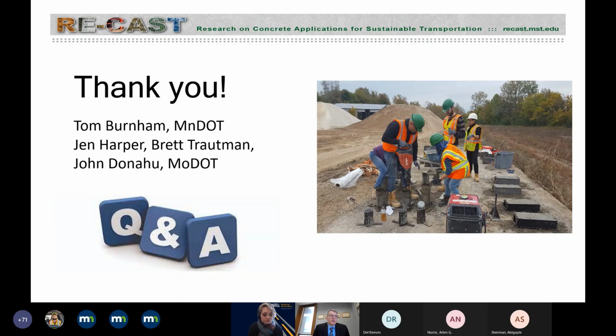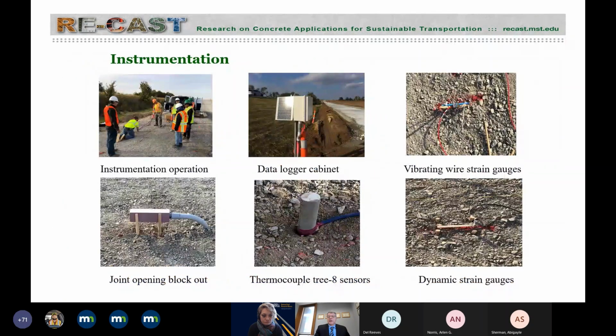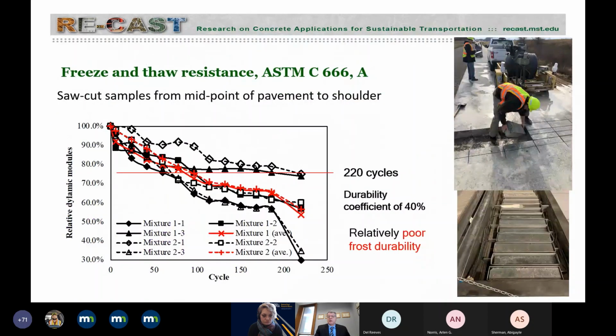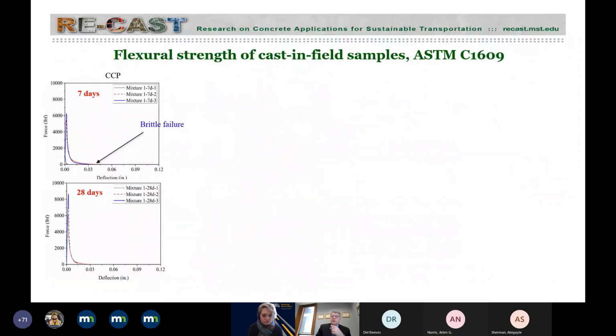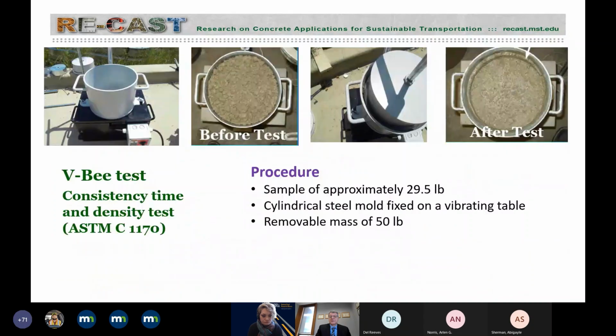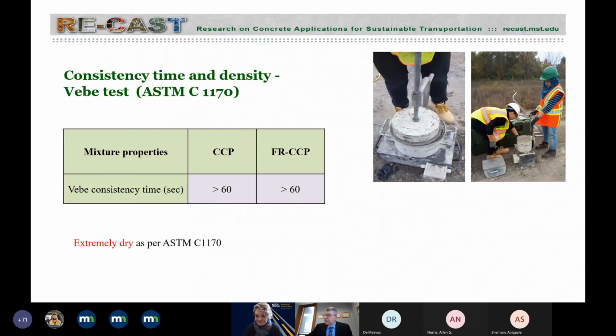So the contractor thought that he could achieve high consolidation using the equipment that was specified, given the limited thickness of this pavement. But obviously, from the results and the large spread that we observed from the shrinkage tests and some of the flexural tests, and the density itself, the consolidation was not very adequate. So it's a combination of consolidation and mixture proportioning. The mixture proportioning was extremely dry, obviously, and the consolidation, in my opinion, was not adequate. Someone responded to that set of questions by saying: correct, the density data showed a major issue in the research, starting with the method of construction and sampling.